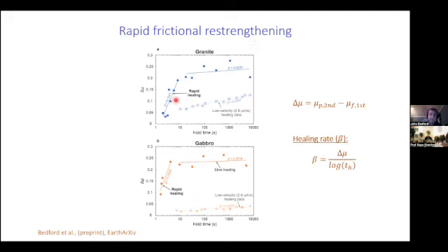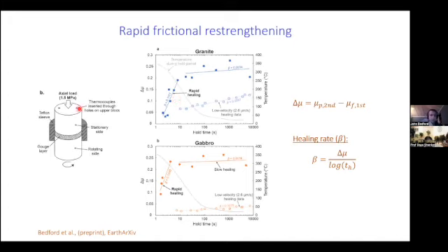But obviously the big difference between low velocity tests and high velocity tests is you get a lot more shear heating at high velocity. So what we did is we drilled some holes in the top of our experimental forcing block and put some thermocouples through them, and so they were basically touching the top of the gouge layer to monitor the temperature during the experiment. So what we found is that the peak temperature we reached during high velocity sliding was around 350 to 400 degrees Celsius. And then that decays during the hold period.